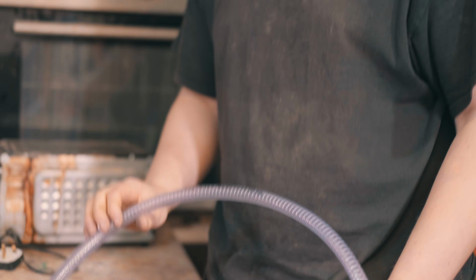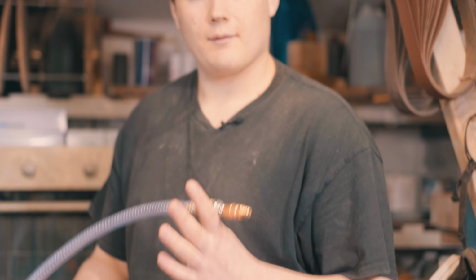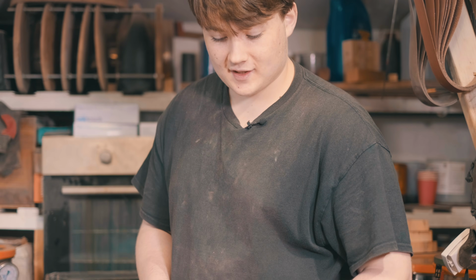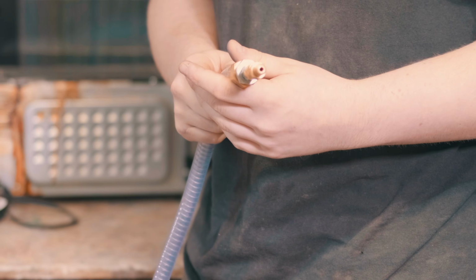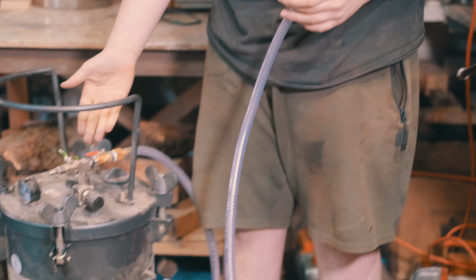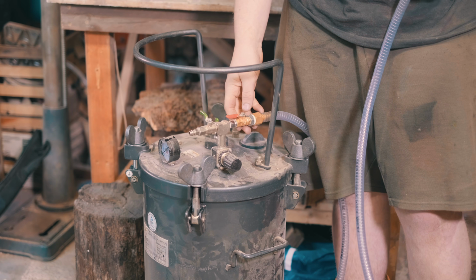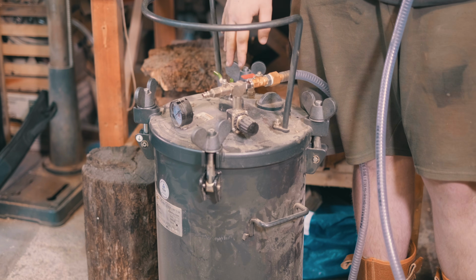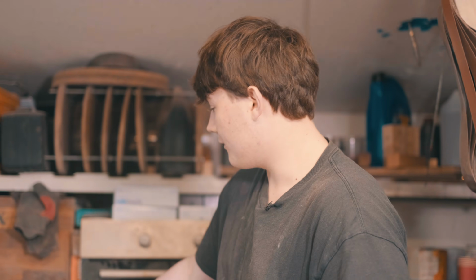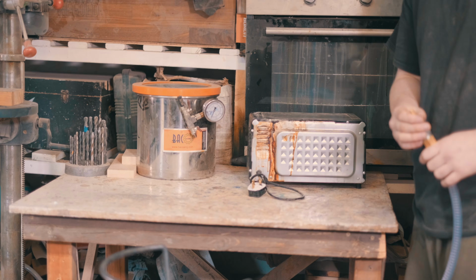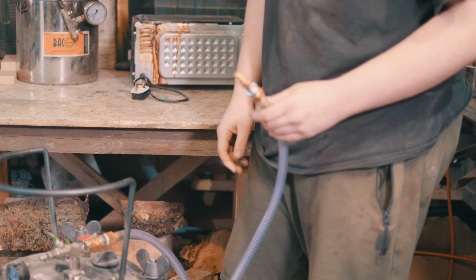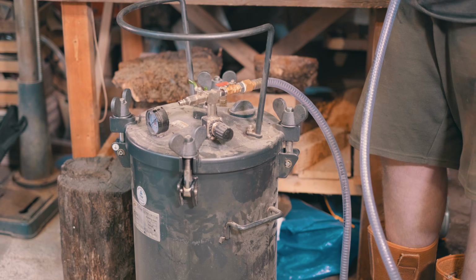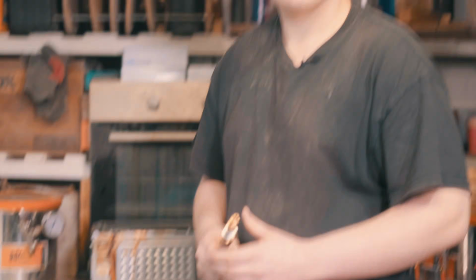One of the modifications that I've made to the pressure pot is the addition of a vacuum hose. Through various fittings and connectors, this will attach to my vacuum pump and can pull a vacuum through my pressure pot. If I seal up this end, I can create a near full vacuum in this pressure pot, exactly like the vacuum chambers, but it's just much bigger. This will then speed up the process because I can run 8 or 9 colours in a single chamber instead of 1 in this chamber. And also it allows me to get a tighter fit on the lid because it's pulling it down, and means I'm not doing lots of changing around, so I can process more.